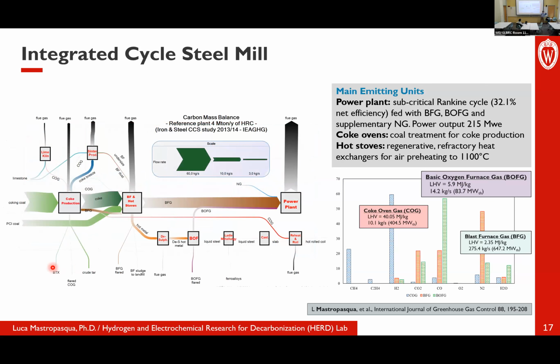Here we looked at the carbon balance, so which are the units that emit more CO2 in a conventional steel plant. And you can see that the biggest is the power plant. Each of these steel plants has its own power plant to power the manufacturing process. The power plant is usually not a very efficient power plant. It's a steam cycle that operates at like 30% efficiency. So it emits, percentage-wise, a lot of CO2. And then the others are the coke production process. Again, coke is very difficult to eliminate. And the blast furnace. So the blast furnace is this process here.